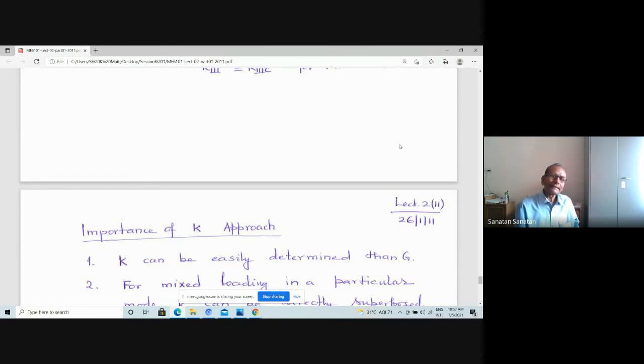And as the critical condition is reached, he also showed that this intensity factor reaches a critical value, thereby meaning that a critical quantum of energy is available for crack extension. So this stress intensity factor has importance, in that it gives you the understanding of stress and strain around the crack tip, and the quantum of energy that is available for crack extension.